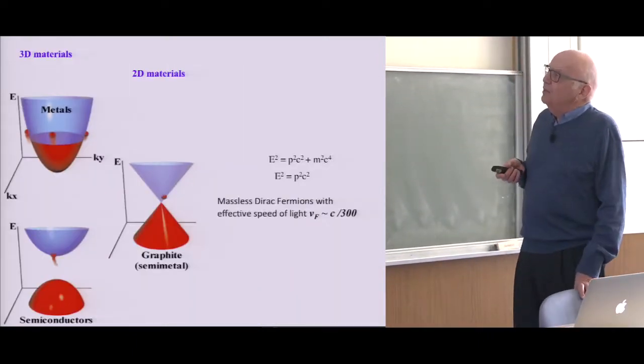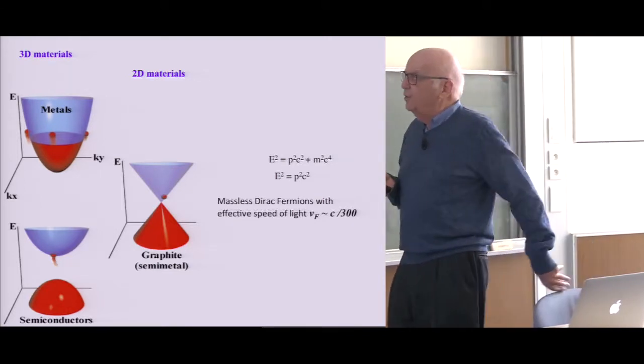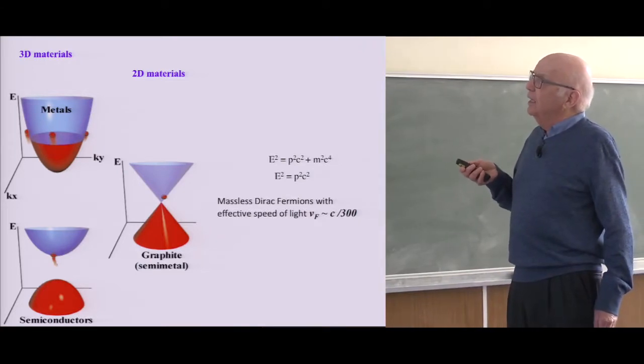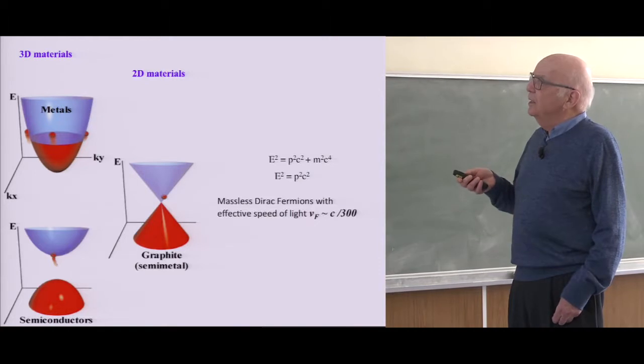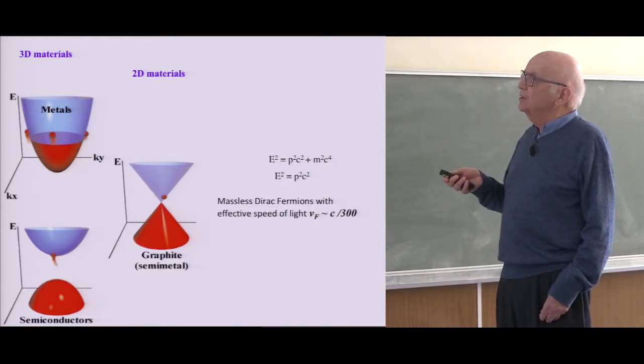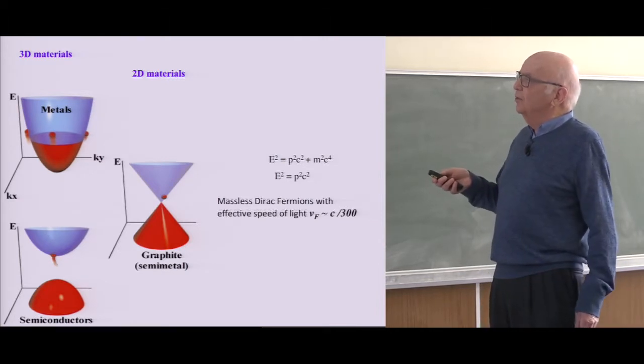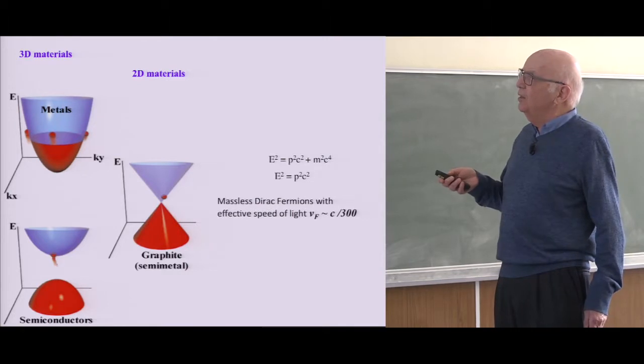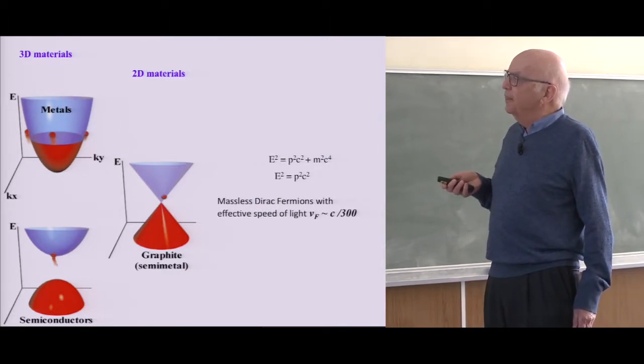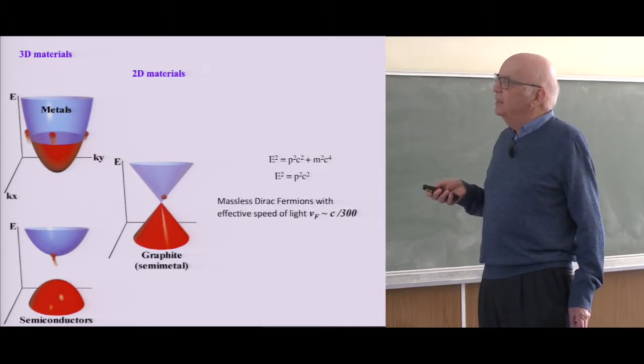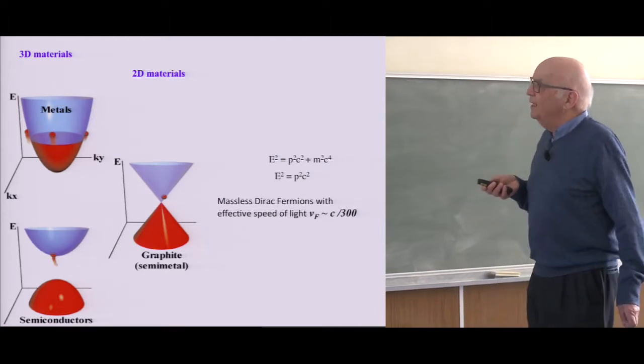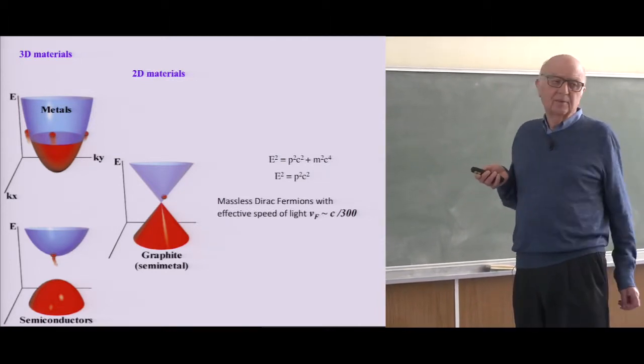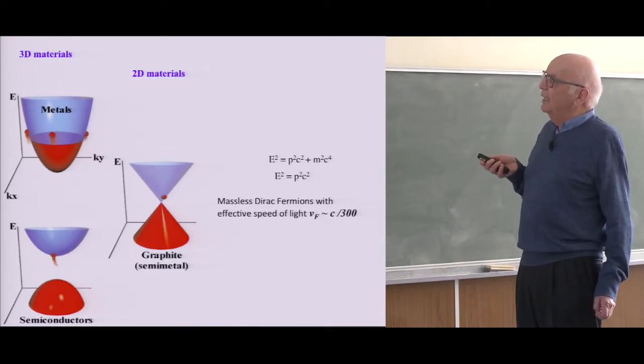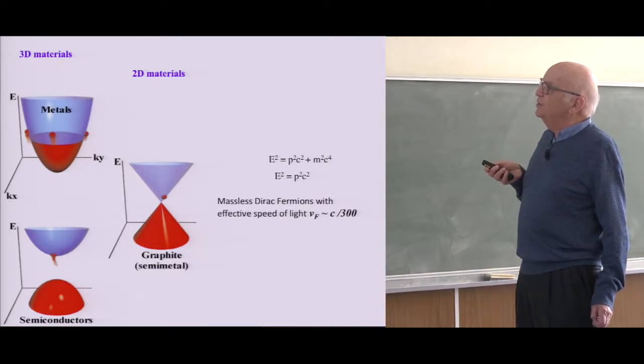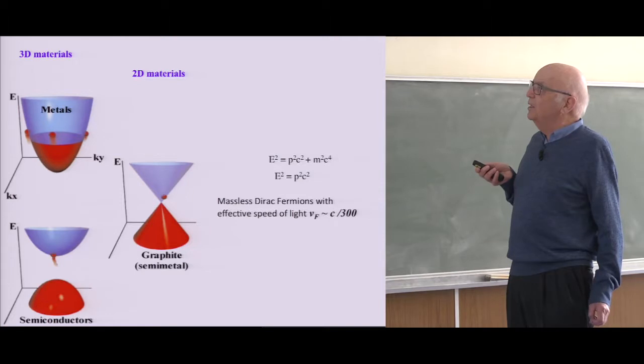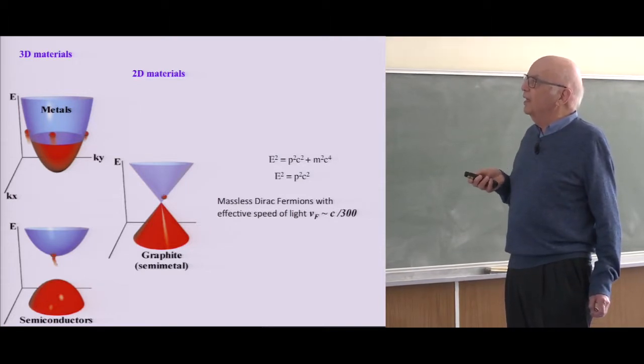So one of the more interesting aspects of graphene is that if you look at a regular metal and you plot the energy versus wave vector, it goes like the square. So the energy goes like the square of k, or the square of momentum. And for a metal, the Fermi energy is here, so there's no gap, and you get excitations. For semiconductors, you have occupied states, and then a gap, and then empty states. For graphene, or graphite, it's a semi-metal with no gap. And the energy dispersion is like a relativistic particle, where the energy squared goes like the momentum squared times c squared, so the energy goes linearly with the k vector, or the momentum.